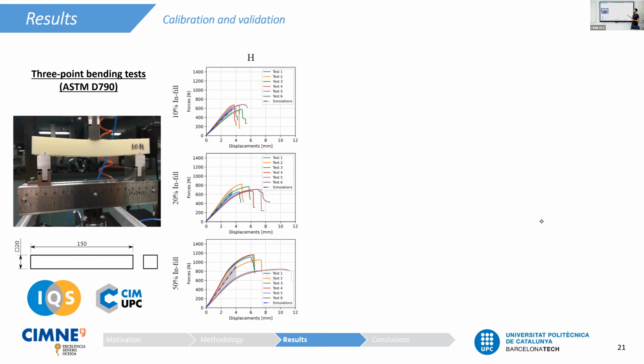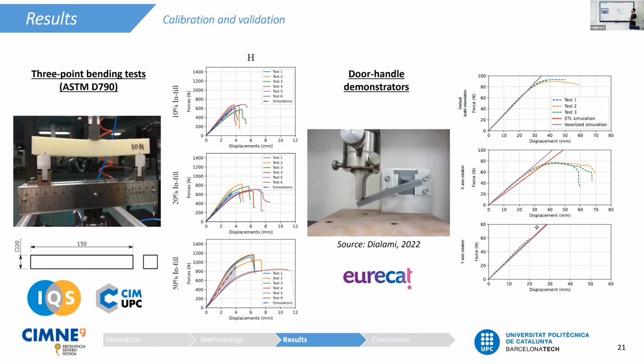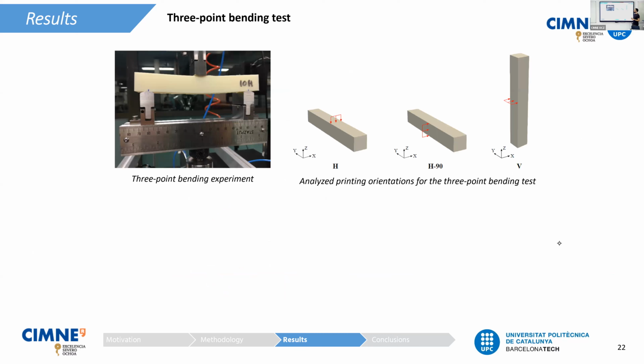This model was again calibrated and validated via several experiments. First of all, it was calibrated and validated in the linear regime. You can see, basically, that the simulated force displacement curve always falls within the experimental range in both experiments. And once this model was calibrated and validated, we performed the analysis for the non-linear regime. For the non-linear regime, we basically did 2 experiments. The first one is this standard and classical 3-point bending test, in which we are analyzing 3 different printing orientations. The first one is horizontally printed, and the load is applied in the top face. The second one is horizontally printed, and the load is applied at the lateral face. And the last one was vertically printed.